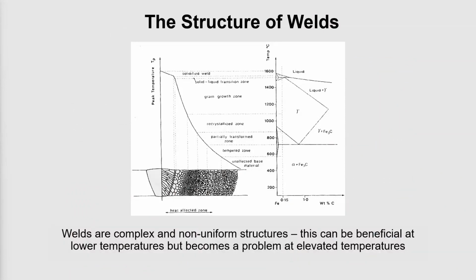In discussing, as we will here shortly, where damage occurs, it's important to understand that, and I think many of you probably do understand this, but for those of you who do not have much background in welding, welds are very complex structures from a metallurgical perspective. When you make a fusion weld, you're obviously adding metal that is up at the melting point of the alloys involved. This means that the material immediately adjacent to the weld deposit will have seen temperatures very near to the melting point of that material, and then there'll be a gradient of temperatures radiating outward from the weld deposit that have seen very high temperatures, but decreasing temperatures as you go away from the weld itself.